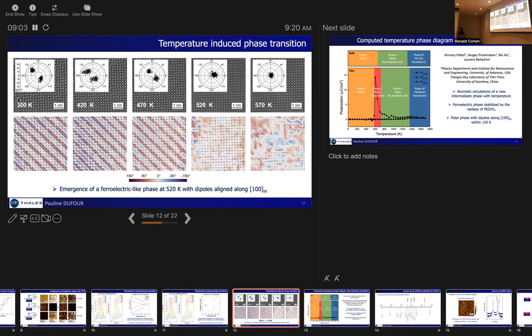So as a remark here, the ferroelectric state emerges at 520 K, which is shifted compared to what we observed electrically. And we assume that applying an electric field in addition to the temperature might reduce this transition temperature.